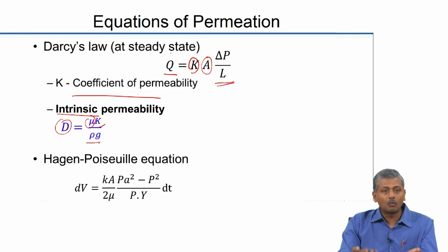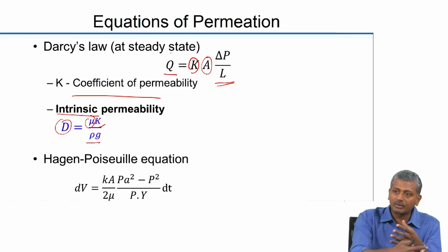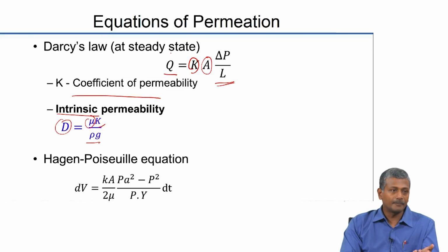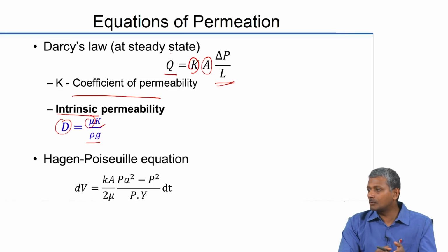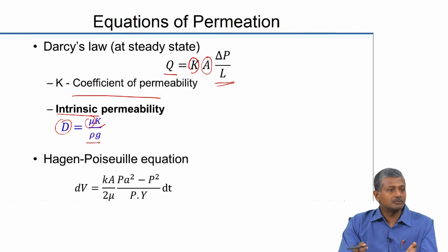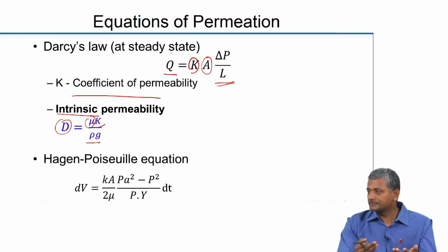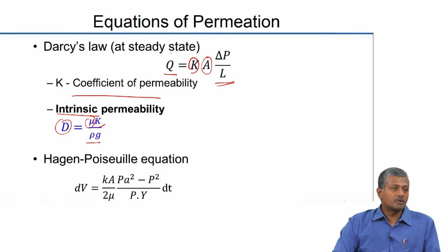First of all, for water to come out through the pores of the concrete itself will take a very long time, and after the water comes out and establishes a steady state, your concrete would have already matured by 10 to 12 days beyond the point where you started the test. So what I'm saying is, to get that steady state, you need to wait at least 10 to 14 days, and in that time concrete has matured already significantly. Because of that, you're not really capturing the true properties of concrete at that point of time. So it's a difficult aspect to establish.